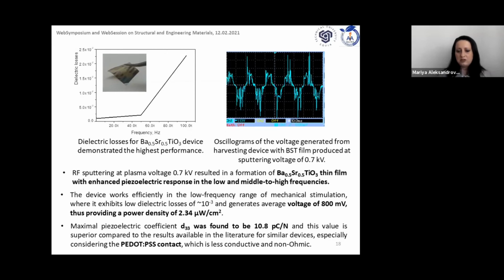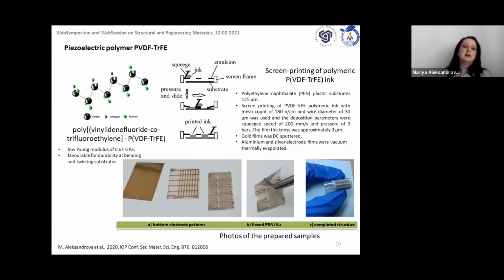Comparing with the literature available for this topic, it is a good value, especially considering that the contacts are not from the classical metal layer. Moving next to the piezoelectric polymers, polyvinylidene fluoride with trifluoroethylene. It is an ink, so it could be screen printed in the form of a layer.